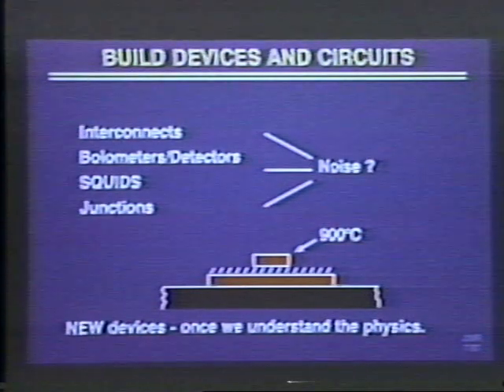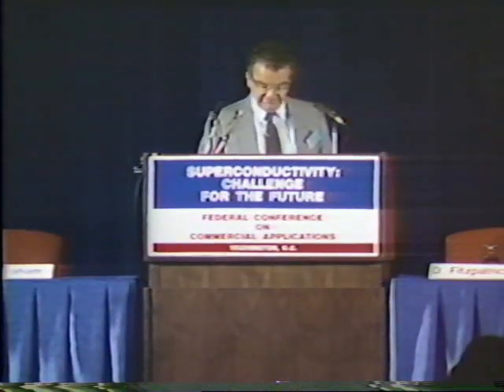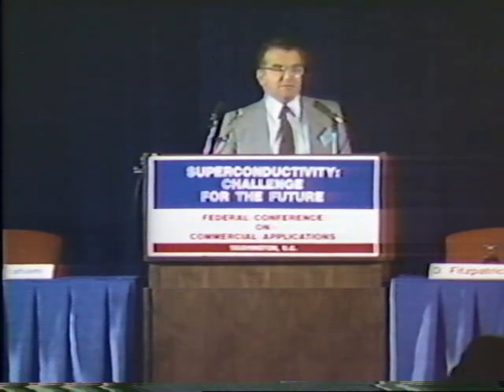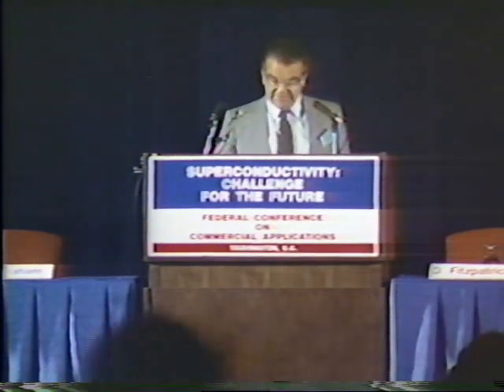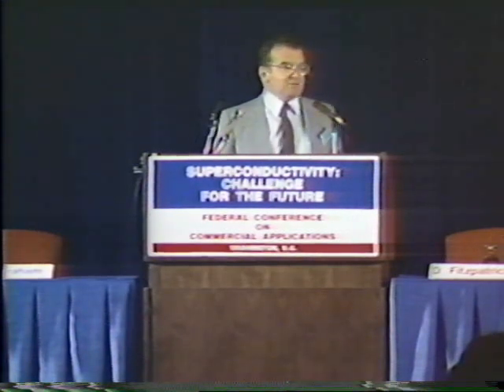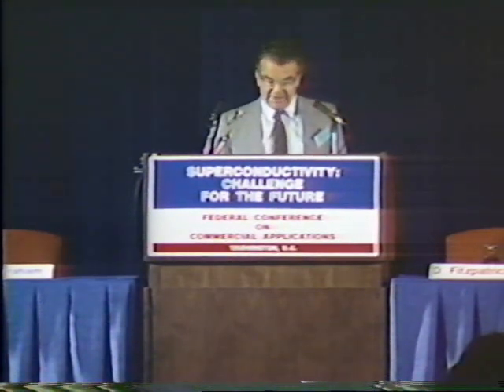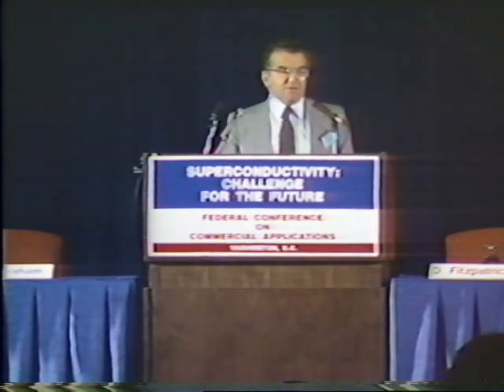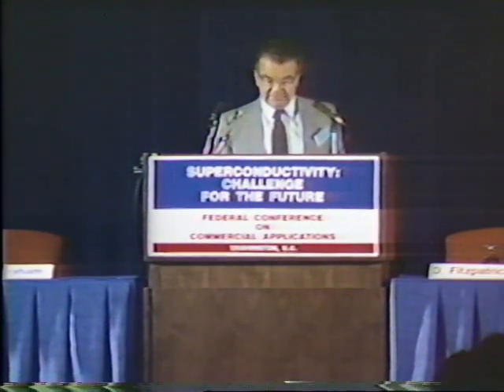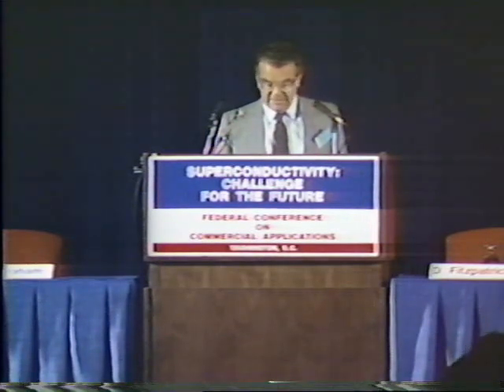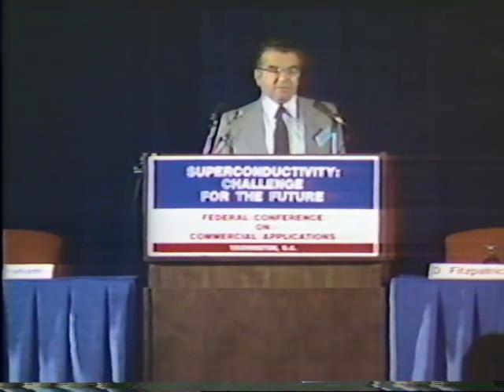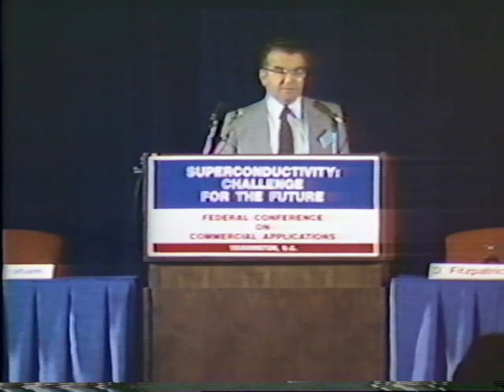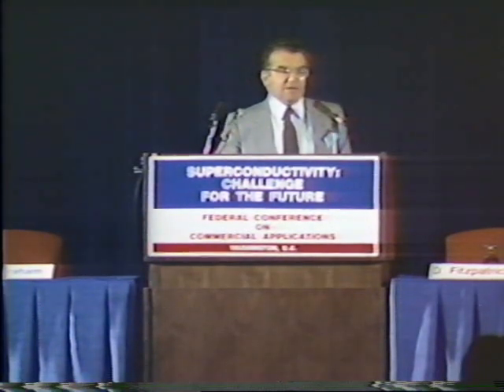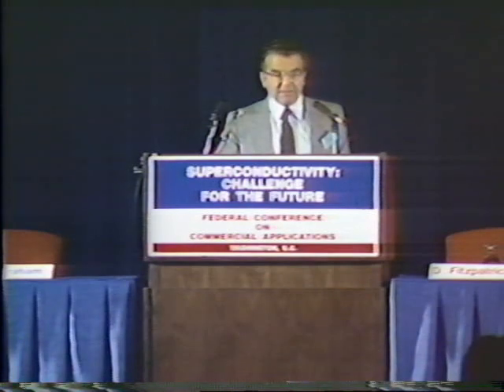And just one comment, I can't resist it, having made tunnel junctions for a large part of my technical career. What I regard as the simplest tunnel junction, and that's probably not shared by many of you, is the two films separated by an oxide junction. Everybody else likes a little narrow bridge. But this is the tunnel junction that is being proposed for all kinds of switching, logic, memory applications, and so on. It involves two films, and Ted Van Duzer said this yesterday, so I'm only repeating it. These two films are separated by an oxide layer of about 20 angstroms or 15 angstroms thickness in order to get a decent tunnel current through it.